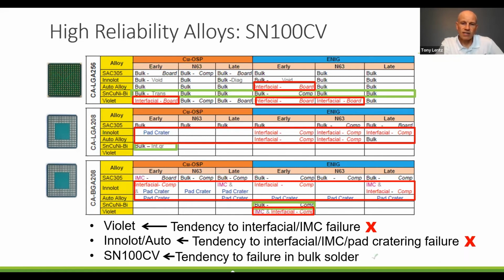SN100CV, on the other hand, in this test tended to fail in the bulk solder, which is a more desirable failure mode. And theoretically, in the field, you could actually repair a failure in the bulk solder if you could resolder the solder joint. Whereas if you have an IMC failure or a pad cratering failure, it's very difficult to rework that. And so that wouldn't be repairable in the field necessarily.